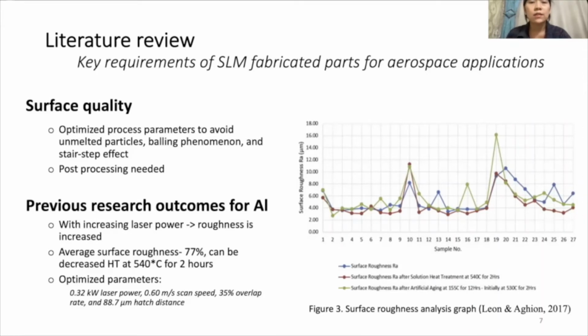Third is that the average surface roughness of most of the samples decreased by 77% after solution heat treatment at 540 degrees for 2 hours. However, after artificial aging at 155 Celsius for 12 hours, initially at 530 degrees Celsius for 2 hours, the surface roughness increased. And the last is the process parameters.